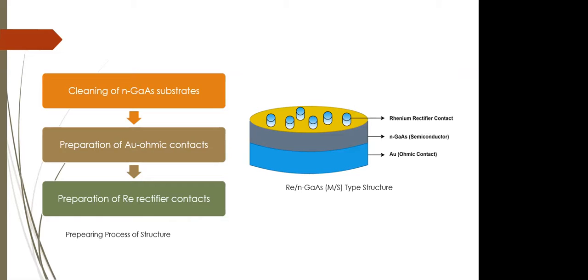Finally, high purity rhenium was deposited on the front surface of the substrate using the pulsed laser deposition technique. The thickness of the rectifier contact is 200 nanometers. The contact area is 1.77 × 10^-4 centimeters square. Thus, the rhenium N-type gallium arsenide MS contact with native oxide layer was prepared.